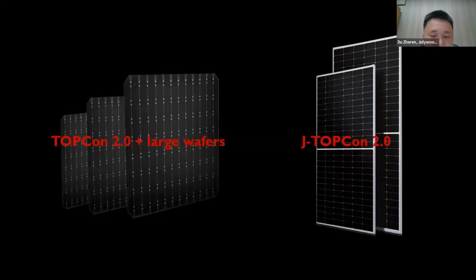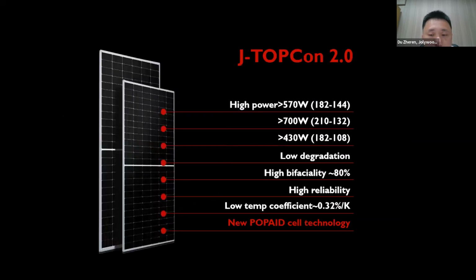So actually we have applied our TOPCon 2.0 technology on large wafers, and we are able to provide both M10 and G12 size cells. Yeah, the new technology and the large wafer actually make our J-TOPCon 2.0 products more competitive. And our product has very high module power. The module power is more than 570 watt for M10 size with 144 half cells. This is about 30 watt higher than the standard PERC modules with the same configuration. And we also have module power more than 700 watt for G12 size with 132 half cells. The module power for M10 size with 108 half cells is more than 430 watt.